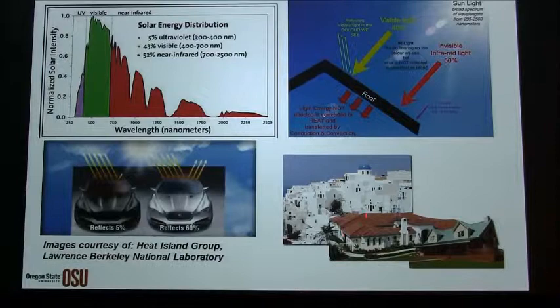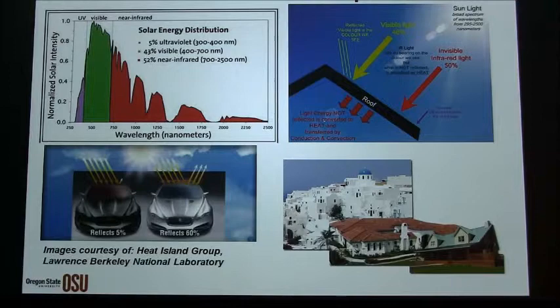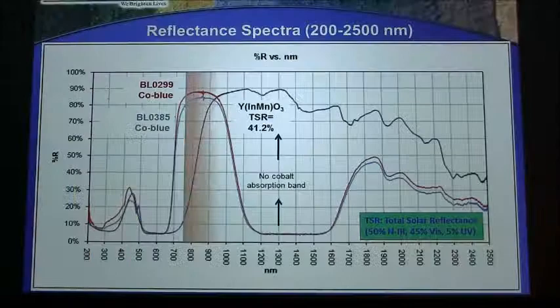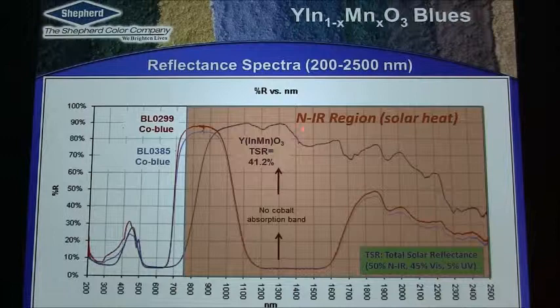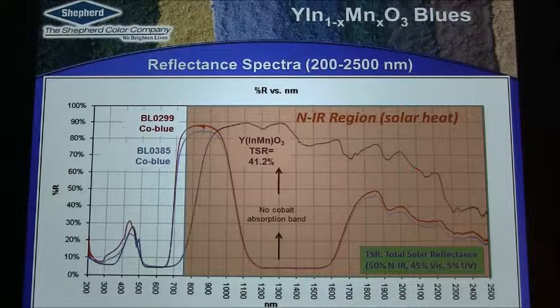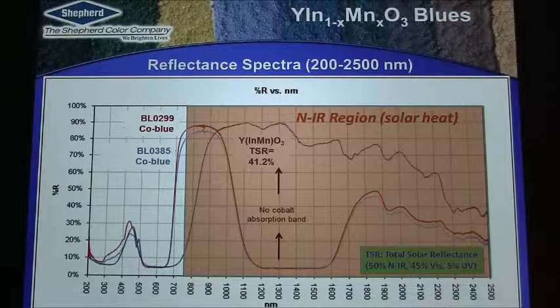But there's always interest in painting the roofs with colors, or with paints, which can reflect infrared radiation. In California, there is actually a minimum standard: you have to paint the roofs with paints which can reflect at least 20% of the solar radiation. So Shepard and our company did the evaluation of our pigment versus the cobalt blue. As you can see, it reflects nearly 90% of the near infrared radiation. That means it can reflect most of the heat coming out of the sun actually.